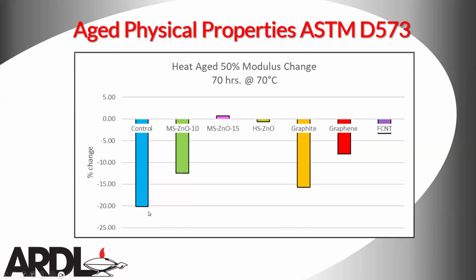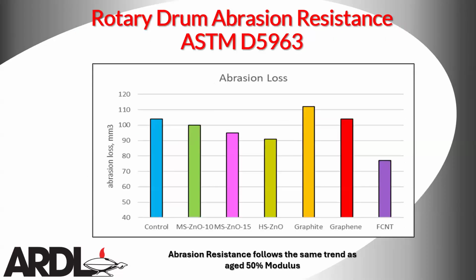So if I look at my control here, you can see I lost 20% of my 50% modulus. So my compound is softening quite a bit. And then what you see here is that your higher level of zinc oxide, or your highest surface area zinc oxide, and the functionalized carbon nanotube had the least amount of change. So ultimately, those 3 fillers at those levels and those types are making my compound more thermally stable.